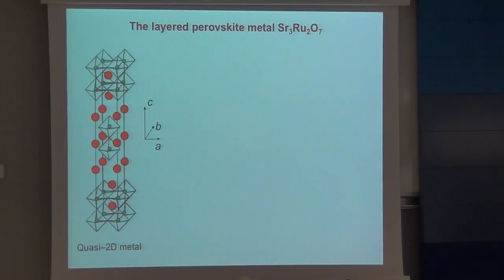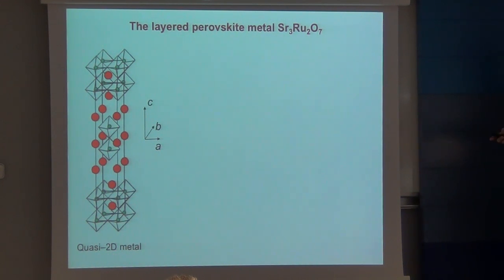So now onto the material that we've studied a lot. And this is another metal. It's not a high-temperature superconductor, but it's an interesting so-called quantum critical system, strontium-3 ruthenium-2 oxygen-7. And it consists of bilayers of ruthenium oxide separated by spacer layers. So there's a strong bilayer coupling of the electrons, but there's a very weak coupling between bilayers. So it should be thought of as a two-dimensional stack of bilayers is essentially the way to picture what's going on. Almost all the charge flow is in the plane.